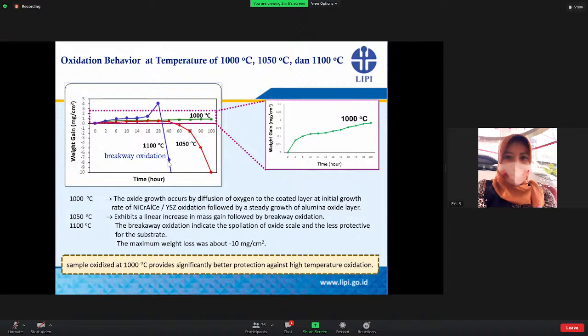shows a linear increase in mass followed by breakaway oxidation, so it is not protective for the substrate. If we measure the weight loss, it was about minus 10 milligram per square centimeter. Therefore, it implies that the sample oxidized at 1000 degrees C provides significantly better protection against high temperature oxidation.